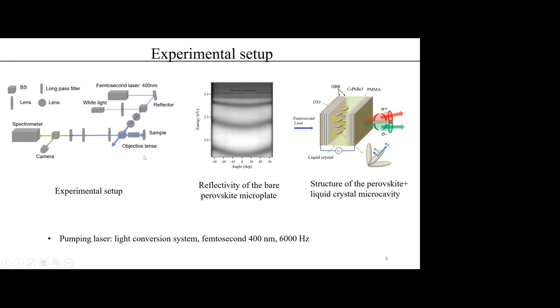Up to now, polariton lasing based on perovskite microplates cannot be realized under CW optical pumping. The excitation source we use is a commercial 35 femtosecond laser with a wavelength of around 400 nanometers and a repetition rate of 6,000 hertz. The size of the laser spot is around 60 micrometers, which is much larger than the perovskite microplate.